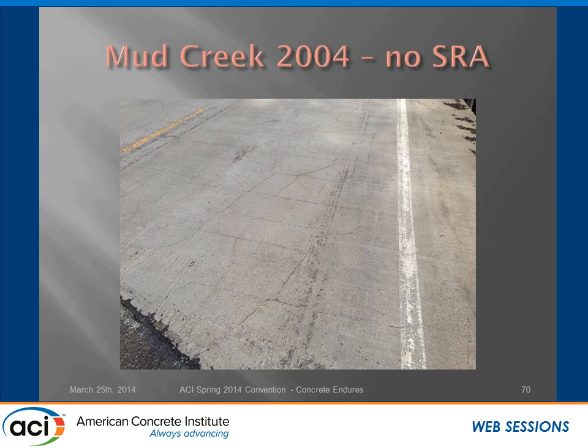We did it in two stages, kept traffic on one side while we worked on the other. And we only cured this for 3 days. And that's important to come up later. But we didn't really have that good of luck. This was a hot mix. We wanted to set up fast so we could put traffic over on it. We had flaggers out there 24 hours a day. So the sooner we got strength, we could put traffic on it, do the other side, and get out of there.